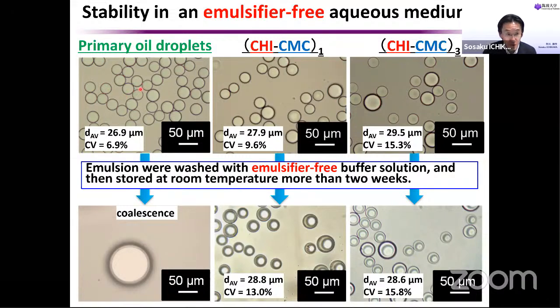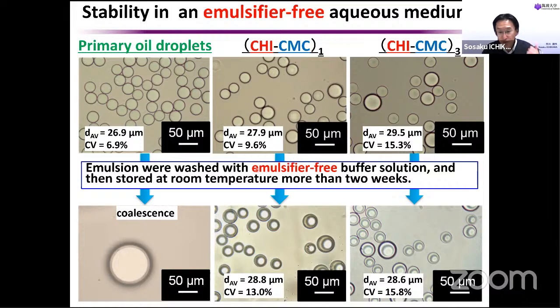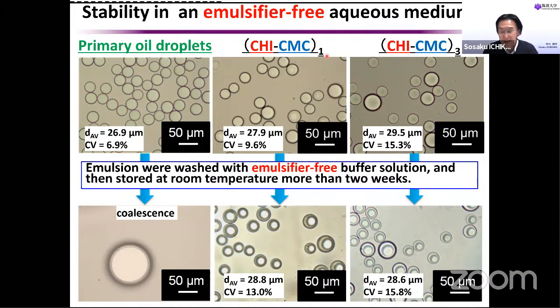In this primary oil droplet emulsion, most of the oil droplets coalesce. They cannot keep their droplet form. They make just an oil phase, not dispersed. But in the case of the chitosan and CMC coating, even after the removal of the emulsifier, we get oil droplets. It means these oil droplets can be stabilized by these coating layers. So it's possible to make an emulsifier-free emulsion using this technique.